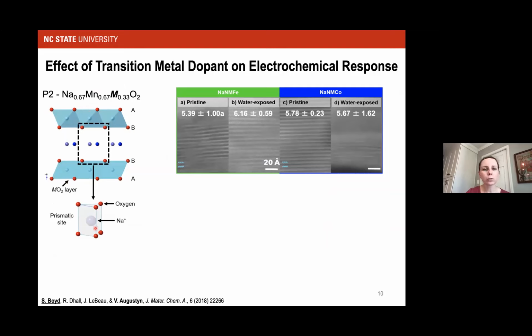And so the structure of these materials, these are all layered materials synthesized at high temperatures, about 900 degrees Celsius. They contain layers of transition metals. Predominantly, those layers consist of manganese, separated by layers of sodium cations that are in a prismatic coordination. The P2 just stands for the prismatic site, and the 2 is the stacking sequence of the oxygens in the layers.